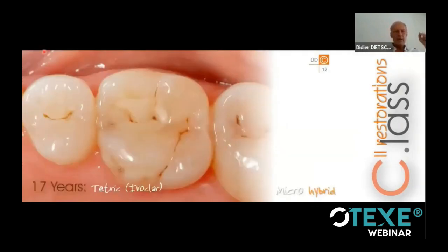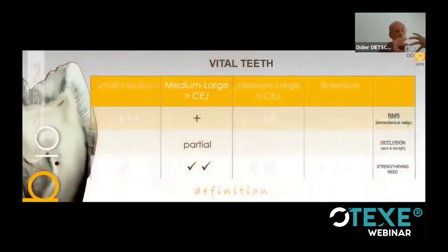You see here another case, 17 years after placement. And I take the opportunity to show you a little defect here. What is that? It is bonding. We used thick bonding layers in those days, but we should not have a thick bonding layer on enamel because this area will wear more rapidly than the restorative composite. Otherwise, the restoration is perfectly well bonded. There is no problem, but we had a slight margin degradation because of too much bonding applied on the enamel.